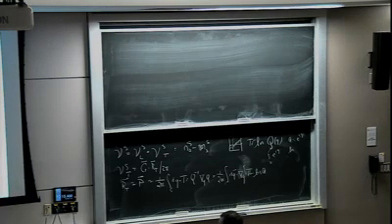If I take this unit cell, which is the natural one to do, then when I calculate q, there are poles in z. So we calculate a number which is the number of zeros minus the number of poles. When I calculate the surface one, because I'm only going in the forward direction, it's only a function of z, and they're only zeros. So it depends on which unit cell I choose.